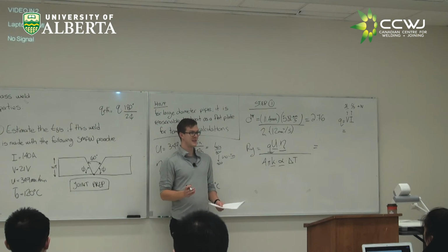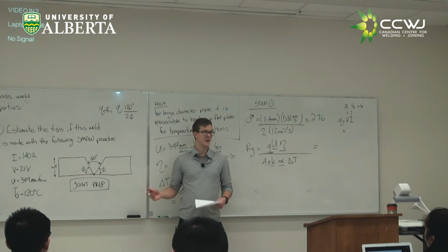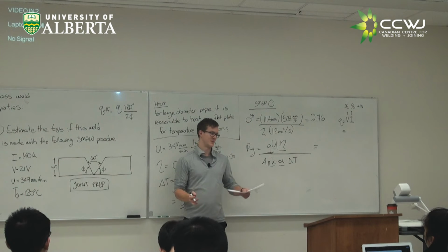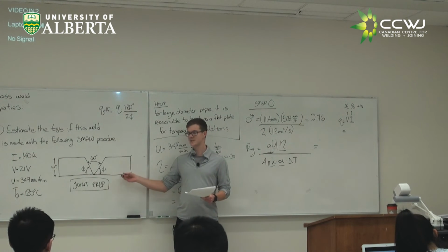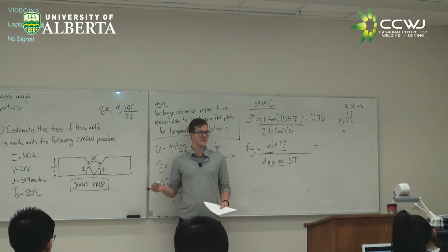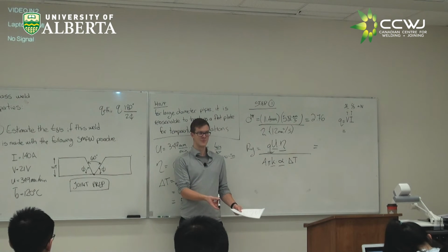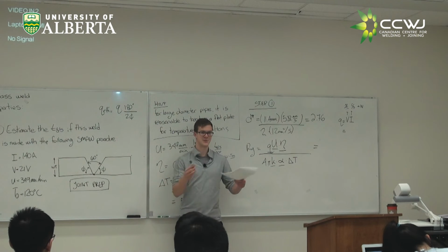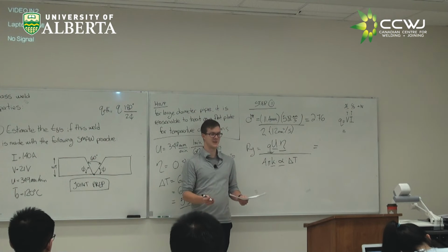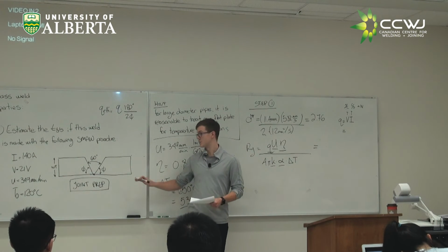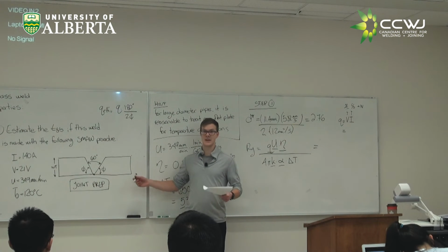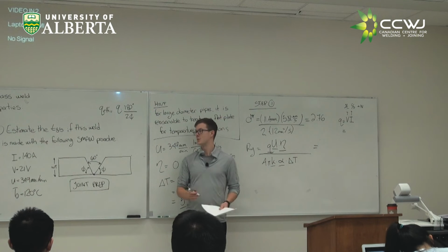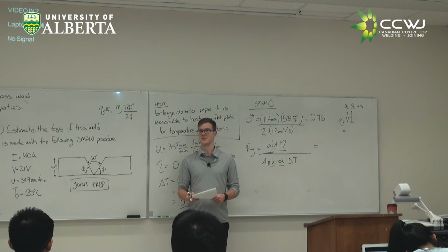In either case, if we use this factor and get a result which suggests that we should not use it, then we're going to have to double check. Does that make sense? If we use this factor, we're assuming we're in the thick regime. If we get a result that says we're in the thin regime, we have to go back and double check that result, because it could change. If we don't use this factor, we're assuming we're in the thin regime, and if we get a result that says we're actually thick, we'd have to apply this factor and recheck the result.